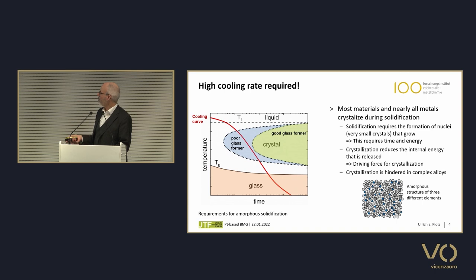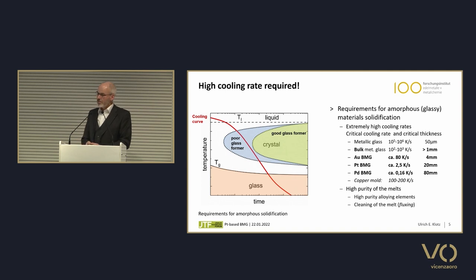Now, most metals don't show this. And this image is showing this amorphous structure. It's promoted by several atoms of different kind, this irregular amorphous structure. So most metals are not doing this. The effect of bulk metallic glasses is only known since the 1960s, because in order to pass by this crystalline nose, you have to cool extremely fast. So for a metallic glass, you have to have 100,000 to 1 million kelvins per second, which is extremely fast.